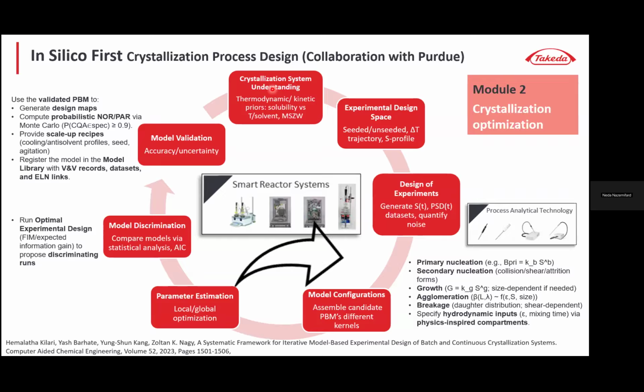At the center is a population balance model with the mechanisms we expect to matter: primary and secondary nucleation, growth, agglomeration, and breakage. Hydrodynamics also has to come into the picture here, because collision environment, shear, and mixing can influence several of these kernels, as we know. We then use optimal experimental design to choose a small number of runs that are truly informative, and it helps us with both parameter estimation and model discrimination.